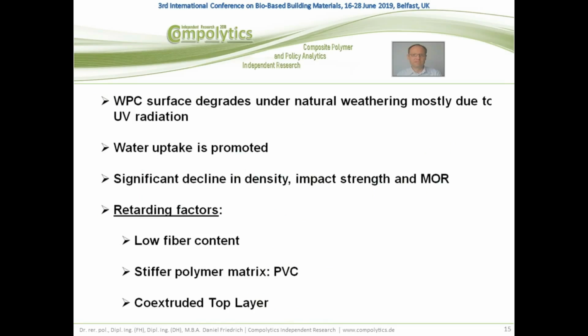So what we can summarize from this sampling with outdoor weathering impact: WPC surface degrades under natural weathering, mostly due to UV radiation leading to polymer chain scission, also leading to water uptake, which is promoted by fiber detachment and by fissured surfaces with micro cracking. And we had a significant decline in density and also impact strength and MOR as the mechanical resistance values went down. Retarding factors we observed was a lower fiber content, which obviously lead to a lower degradation. A stiffer polymer matrix given by PVC also led to lower impacts from natural weathering and higher stability. And the co-extruded top layer is obviously an effective measure to retard the natural aging behavior of WPC in outdoor application.